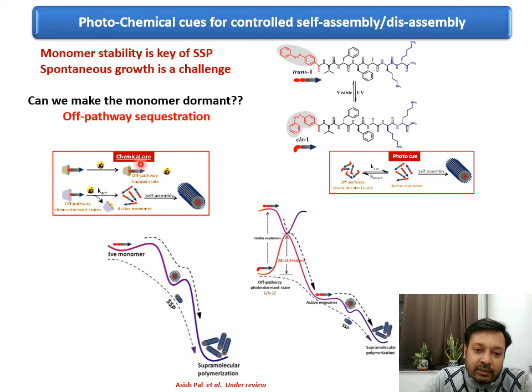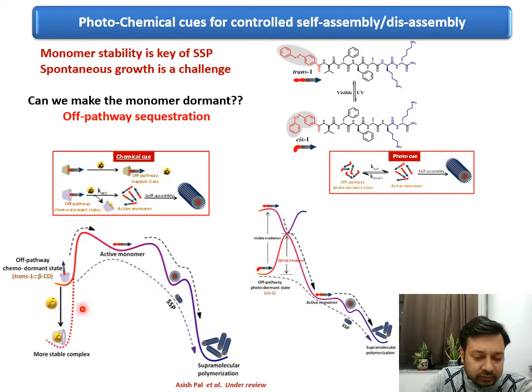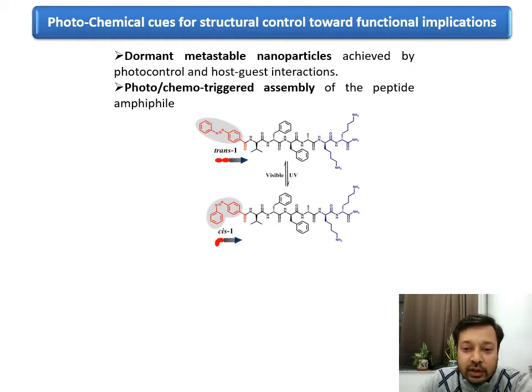polymer. Similarly, we can also do the thing with chemical sequestration, where you can take alpha or beta cyclodextrin, and it can actually trap this active monomer into such a chemodormant state. However, if you put in a competitive guest like adamantane amine, it can actually come back to the active monomer, and it goes for the self assembly.